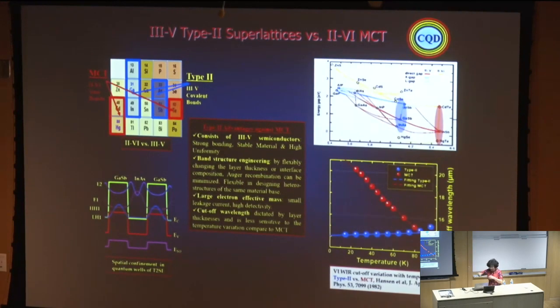And it's a III-V semiconductor, very strong, and the covalent bond is strong. You take this material to low temperature, 10 degrees K, go to 400 degrees, come back, no change. But mercury cadmium telluride, so I will show you, it was a group that was great, they did, and you can see that even in 1982, they made two diodes, one based on the type II, another based on MCT, mercury cadmium telluride. And both of them at 80 degrees K have approximately the same wavelength, 14 micron. When they decrease the temperature to 20 degrees K, mercury cadmium telluride goes from 14 micron up to 20 micron. But for the indium arsenide type II, there is no really big change.